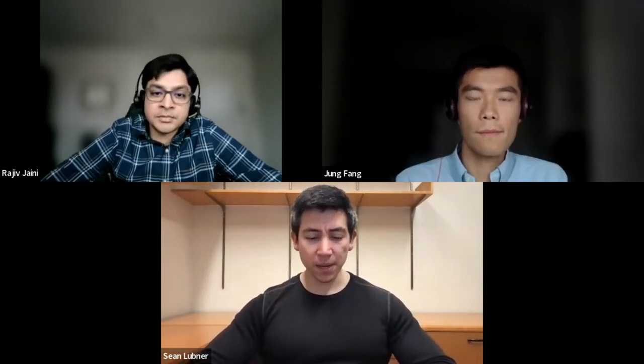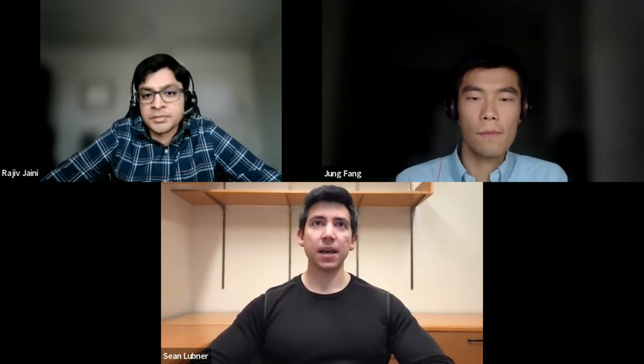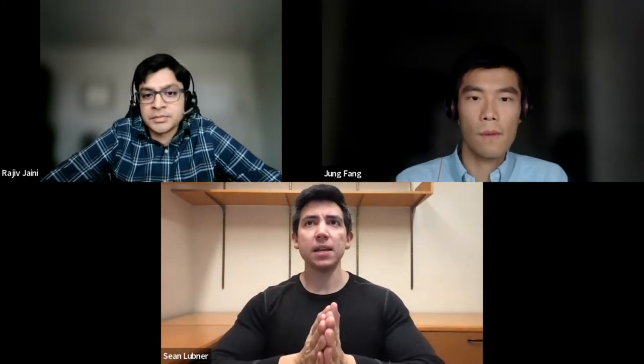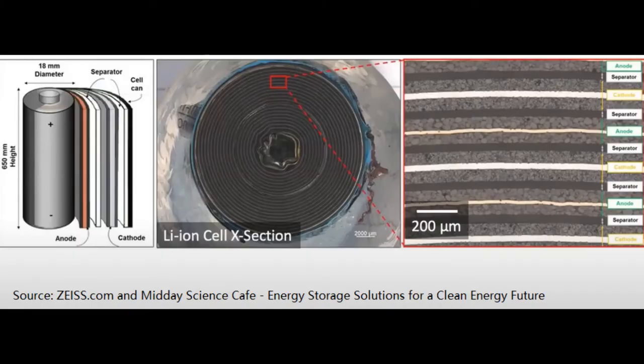And so, one of the big discoveries that we made was that previously, if you had taken the thermal resistance of each layer in a battery, right, if you take a battery and you open it up, don't do that, it's very hazardous, but in a controlled setting, you open it up. Inside, you'll usually, especially if it's a lithium ion battery, see this jelly roll structure, which is a multi-layered structure. Each layer is very thin, tens of microns, about the thickness of a piece of paper. And it's all these layers rolled up together very tightly.